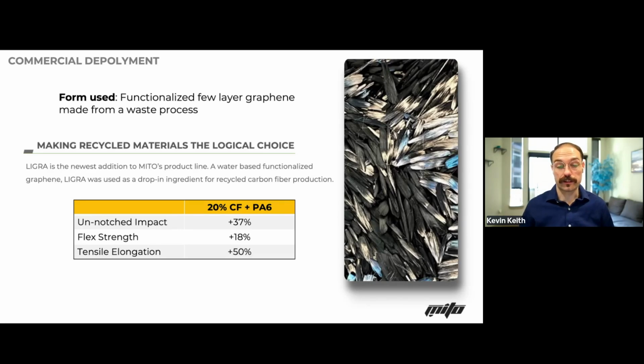That's because when we looked at our recipe book, we looked at our feedstocks, we understood, oh, we're looking for these metrics that we want to increase. And so we looked at the morphologies, we looked at the characteristics, we paired it with some other chemistries that we then deployed into the system to increase the interfacial adherence between the fiber and the polymer. That's why we're getting that tensile elongation increase so high at that 20% loading. If anybody's familiar with nylon 6, it's a very brittle material. And the fact that we were able to do a 50% increase in tensile elongation with such a little amount of material, that's because we understood the recipe book we were looking at.